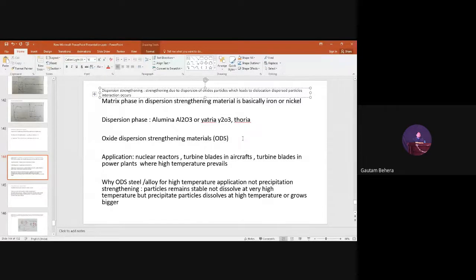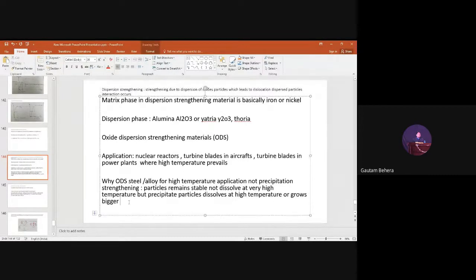ODS steel has very important applications in the nuclear industry, because the service temperature in a nuclear power plant is very high. So we need steels called ODS steels, oxide dispersion strengthening steels, where the steel matrix has a dispersoid of oxide particles, which are very hard, like yttrium oxides and TiO2 particles. Here it is written why ODS steels are alloyed for high temperature application, not precipitation strengthening. Particles remain stable, not dissolving at very high temperature, but precipitation particles dissolve at high temperature or grow bigger, right?